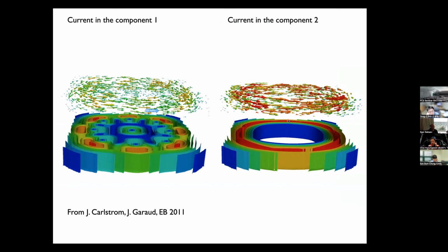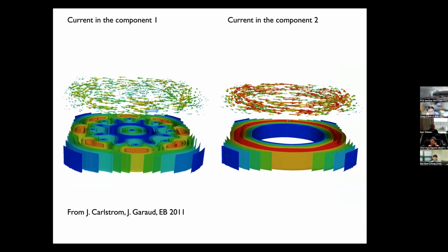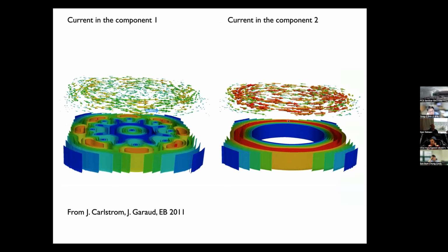So there are now currents simulated by vortices, and then you basically see the existence of 2 types of tendencies. One tendency is to form a type 1-like behavior, that is, to make this cluster as round as possible because of this extra current on the surface of the cluster. But inside, it wants to create as much interface as possible. And that illustrates that the Ginzburg and Landau argument is not generic, because they assumed that you can classify superconductors by a one-dimensional interface.